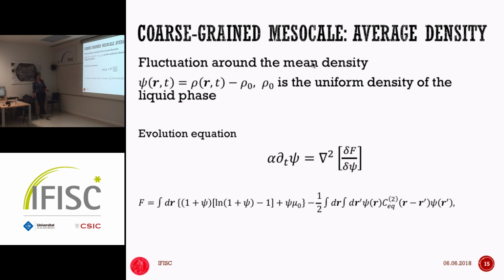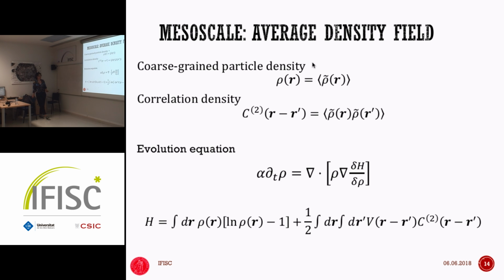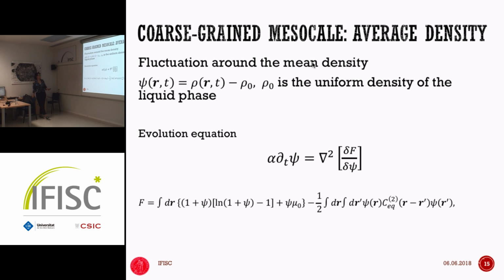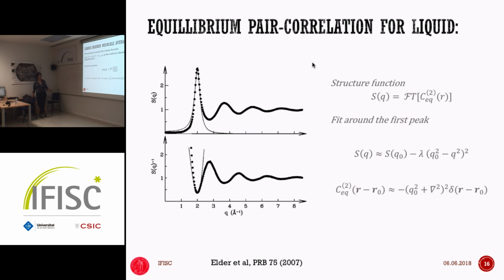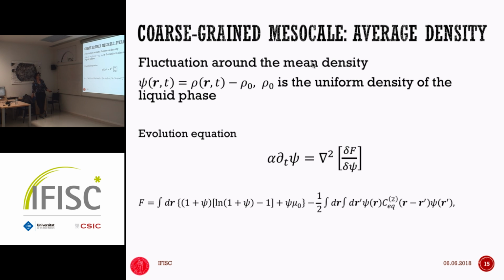Or you can have another approach, which is called the classical density functional theory, where you replace this term here with something else. So first you look at the density fluctuation relative to a reference density. In this case, it's the uniform liquid phase, okay? And you look at the density perturbation around the uniform liquid phase, and you write the evolution equation in terms of this density perturbation, psi. And then there's going to be this coupling that appears in here. And now I can do this decomposition at some level. Well, I think there was another approximation here, that the interaction potential is all buried in the pair correlation functions for the equilibrium, okay? And then if you have an input of this pair correlation function for the equilibrium liquid, you can somehow model this dynamics also outside of the liquid phase.